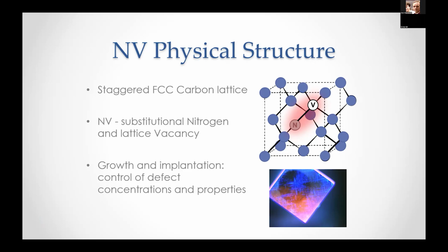And it's important maybe to note that this technology of growing and creating synthetic diamond has really improved over the past, say, 20 years or so, and is still being developed to the point where people know how to grow very well-controlled diamond substrates, controlled in the sense that they can have relatively low strain, they could have somehow controlled defect concentrations, usually nitrogen, but not only, and can even be grown with isotopically enriched content.